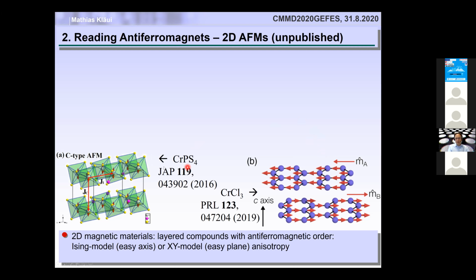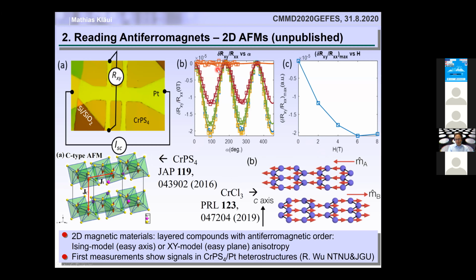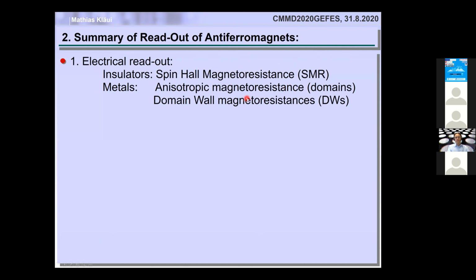And we've been looking at a little more complex antiferromagnet, chromium thiophosphate, which is a bit more stable than this chloride. And we can also get electrical readout of this. So to sum this up, we can read out antiferromagnets, and we can do this electrically by spin-Hall magnetoresistance for insulators. And in metals, we can do this by anisotropic magnetoresistance and also some domain wall magnetoresistance, which I didn't go into right now.